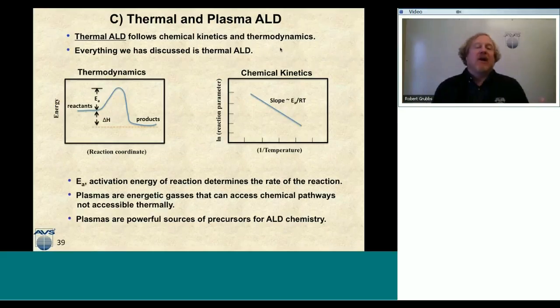And so everything that I've talked about so far is thermal ALD. It follows chemical kinetics and thermodynamics. I've shown the reaction coordinate here and energy. Reactants follow the products. We have this delta H value, which is indicative of how thermodynamically favorable the reaction is. Then I've got this bump right here. I've got this barrier, and this barrier is the activation barrier, and I need enough activation energy to get up over this barrier. And now we're talking about chemical kinetics, and that goes to this plot on the right-hand side.